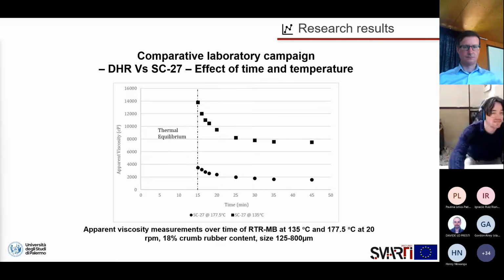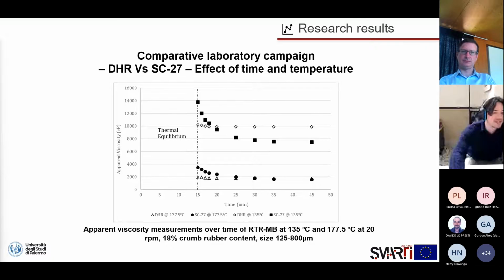After 15 minutes, the motor was turned on, and it's possible to observe that after an initial high value, the viscosity tends to decrease. The same scenario happens when the temperature is high. But let's see what happens when we use a different shape, such as the dual helical ribbon. A stable trend is recorded from the beginning at both temperatures compared to the conventional impeller.